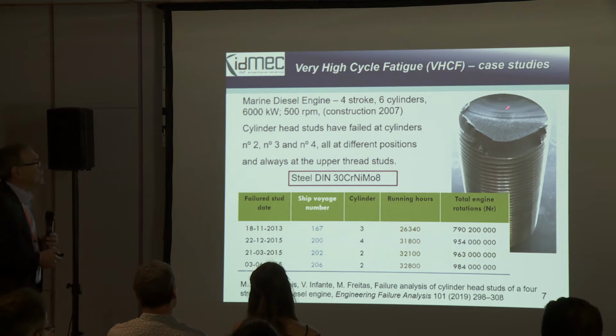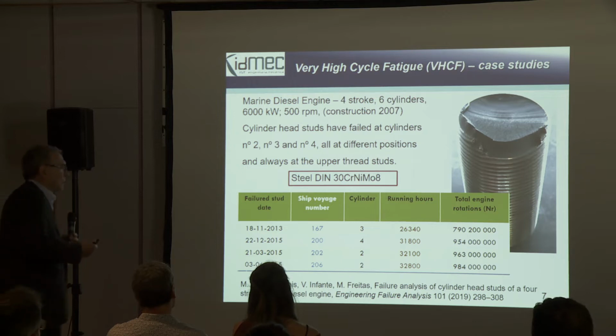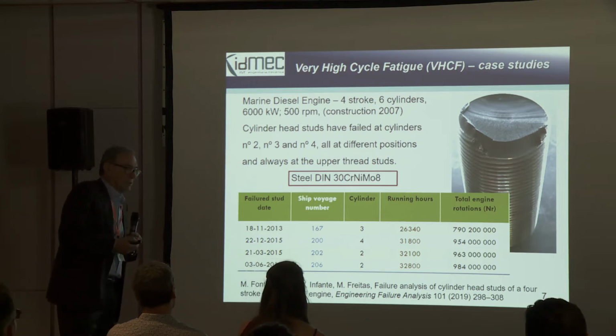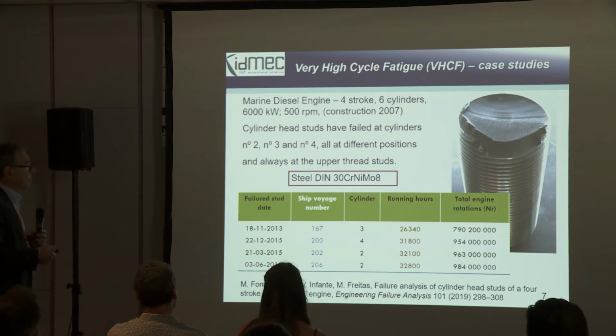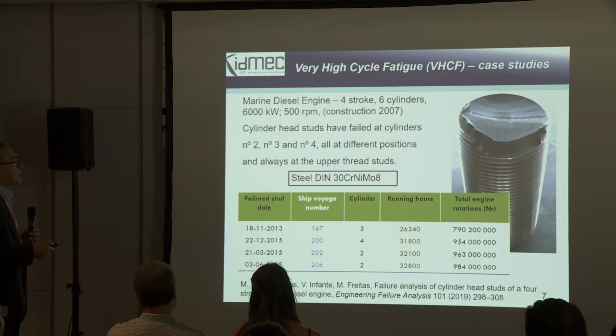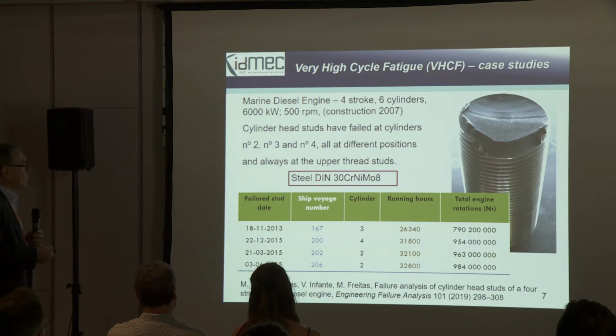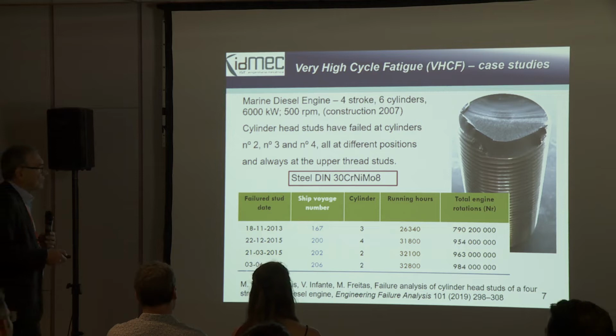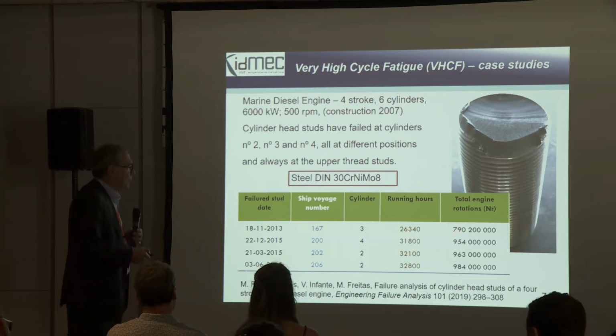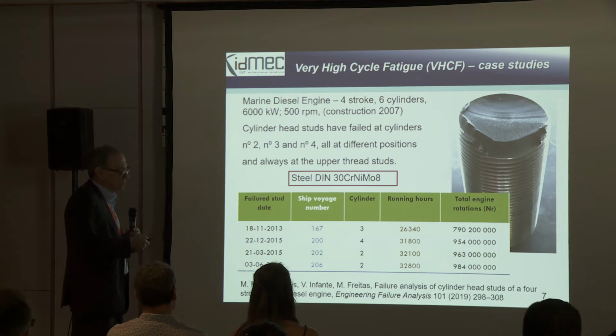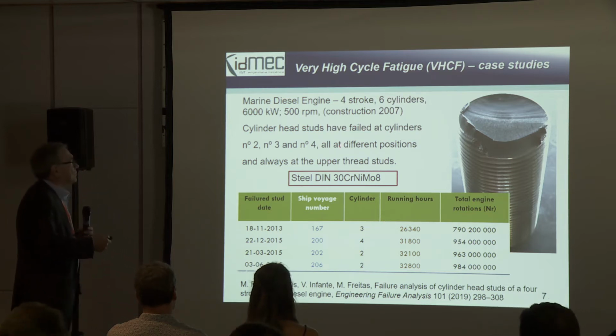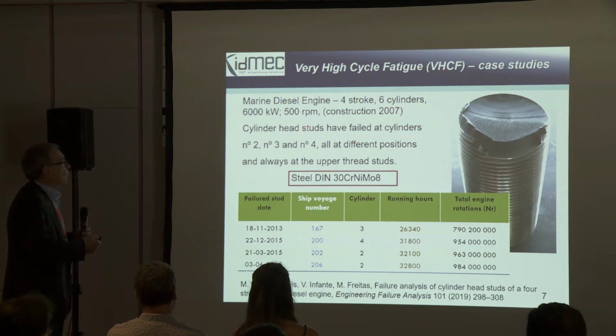I will present here three case studies where this is not a very high strength steel like those ones where the crack initiation is in inclusions, but this is a low alloy steel, but high strength steels. For example, this is a cylinder head stud in engines, marine engines, and you can see that we approach 10 power 9 cycles. This is not a very old engine, so it has 6 years, so there is overload on an engine.